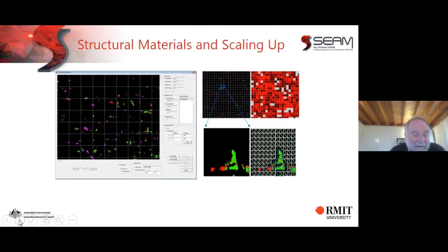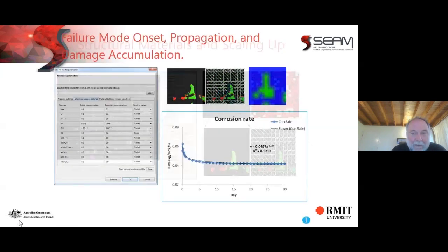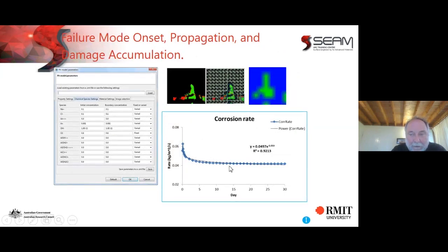Now we need to simulate the metal structure, and we do this. We did a lot of work looking at atom probe to understand what the structure of our aluminium alloys were. And here in the light colours, you can see all the different intermetallics that are providing that strength to the aluminium, but are also acting as corrosion points. And we can generalize this into a generalized microstructure, which we then did. And for each of those intermetallics, we build a little corrosion model and look at how the corrosion rate occurs, and also how the inhibitor can slow down that corrosion rate.